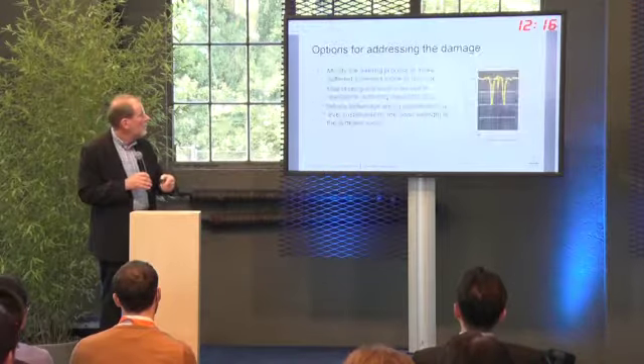So what we decided to do was initiate a small project, just trying to get a better handle on predicting the damage at the welds. And there's quite a bit of work other people are doing in looking at localised damage at welds. Most of it seems to be directed at plastic deformation and wear, and not necessarily rolling contact fatigue, which is something that we're particularly focused on here.